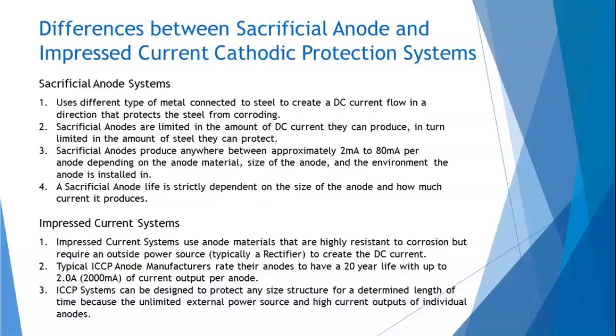I'm going to start off by talking about sacrificial anode and impressed current systems. Sacrificial anode systems are limited in what they can do. The sacrificial anodes produce minimal current, typically anywhere from 2 milliamps to 80 milliamps per anode, depending on the anode material, the size of the anode, and what it's installed in. A sacrificial anode's life is strictly dependent on how much current it produces.